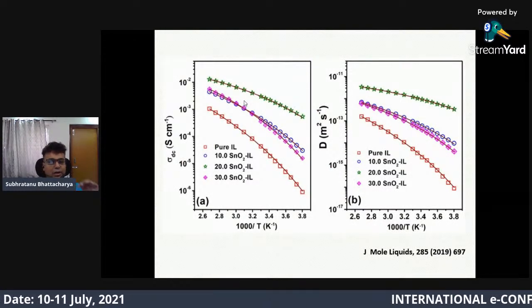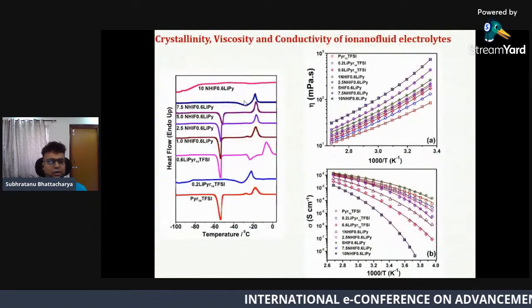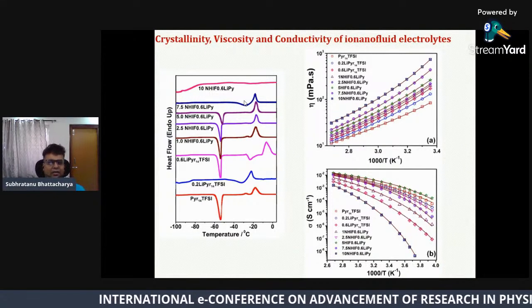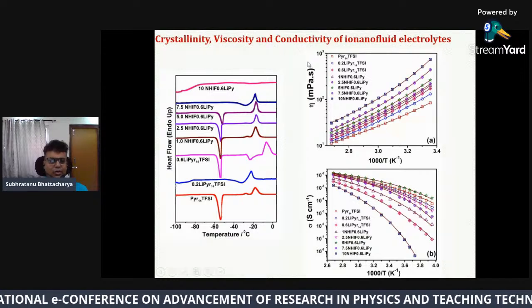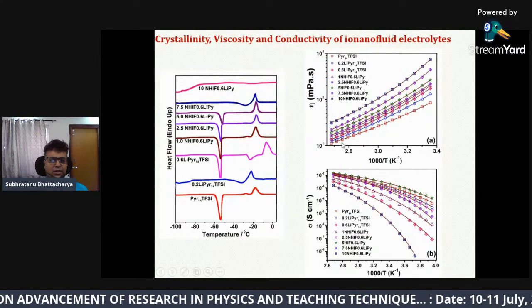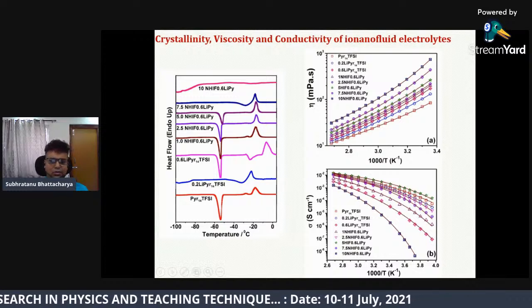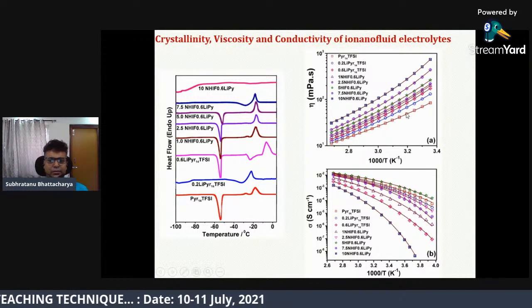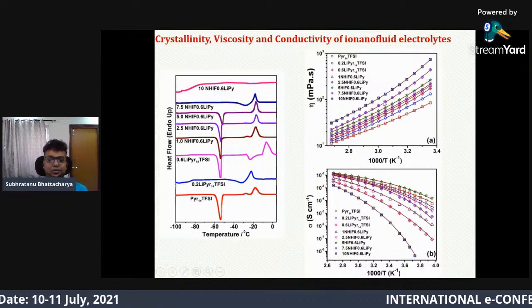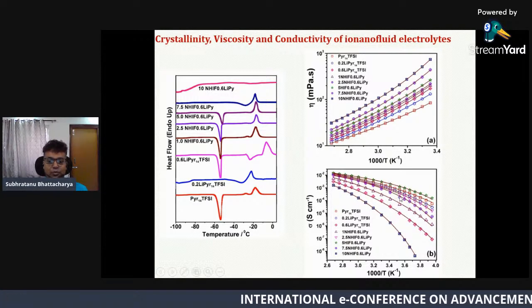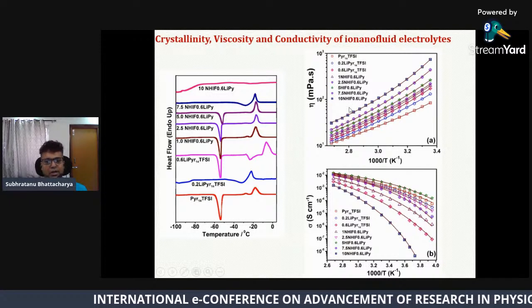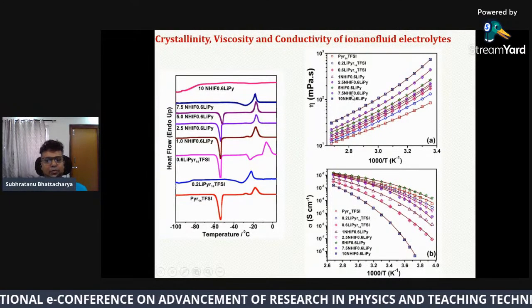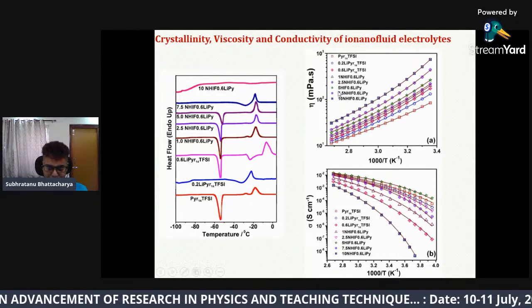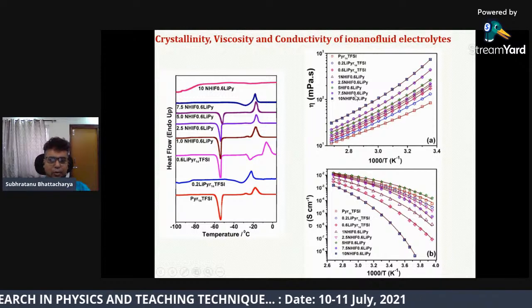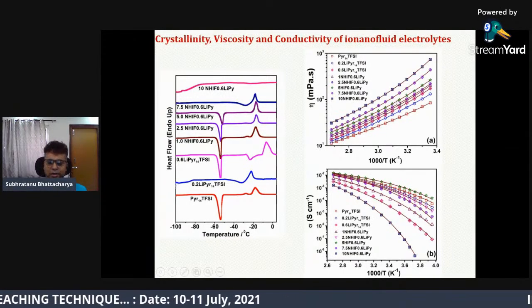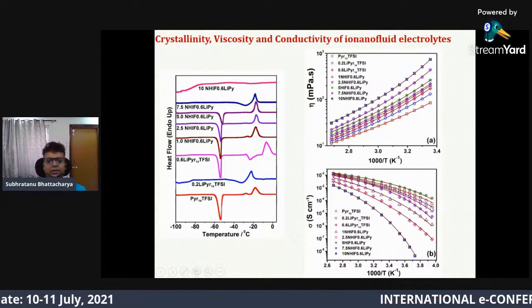That we actually used in lithium batteries. I don't know whether you can understand, but this is very important. This is the temperature dependent viscosity plot. You can see that with temperature, viscosity increases. Simultaneously, conductivity should decrease, but conductivity also increases up to a certain extent, not monotonously, up to say 7.5 weight percent of nanofluid incorporation. In spite of increasing viscosity, conductivity increases substantially.